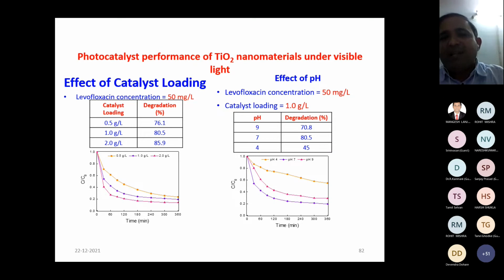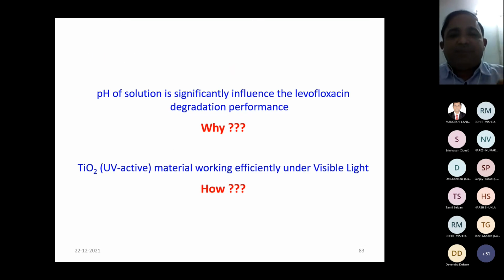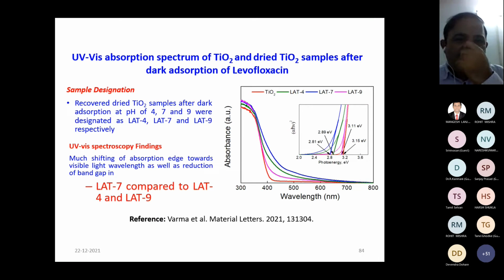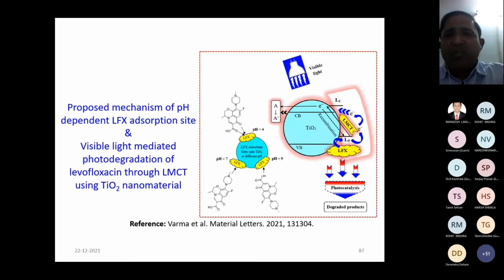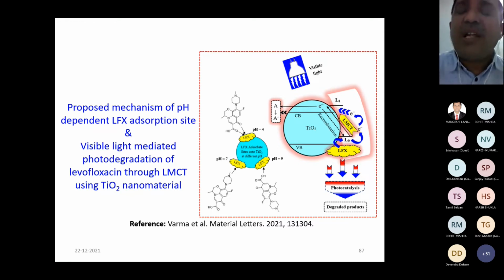For catalyst loading and the effect of pH, as we discussed, but then we tried to identify why TiO2 is working under visible light, and we found that it is because of this LMCT mechanism. I'm not going into detail of the FTIR spectra, but in this LMCT mechanism, the levofloxacin is attached to TiO2 at different pH with different sites, and at pH 7 it attaches to the TiO2 through this N bond, which acts as a carrier to trap the electron, and that is the activity we find under visible light. Because of this finding, it is accepted for publication, and this is a very interesting result.